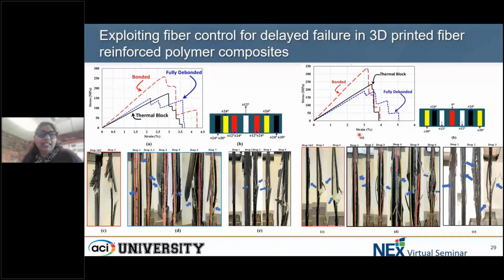So takeaway from these 3 stress strain behaviors of these 3 different bond configurations, there is definitely strength compromise because of the lack of bond. However, what you see as a progressive and almost ductile behavior that we presented before in different configurations is lacking in the fully bonded configuration. So if there are future technological improvements where we are able to achieve this bond in the 3D printing itself, that would be a great benefit because that way we can also maintain the integrity of the material itself.